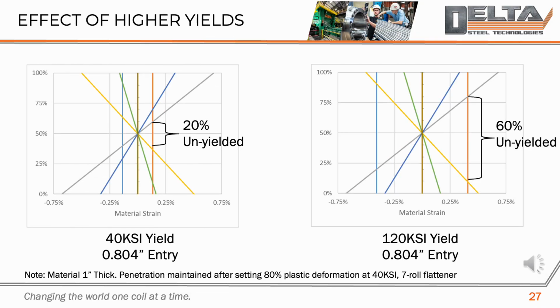On this slide, we're comparing how different yield strengths affect material strain during the leveling process. We have two charts here, one showing 40 KSI material and the other showing 120 KSI material, both with 1-inch thickness. In both cases, the equipment is a 7-roll leveler, and we've maintained the same penetration, aiming for 80% plastic deformation. The key point here is that higher yield materials, like the 120 KSI steel, require more effort to achieve the same level of deformation.